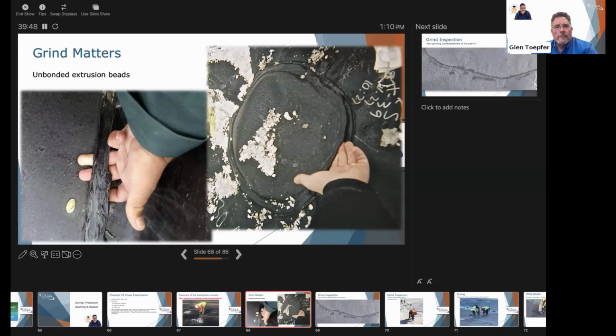And these welds, these extrusion beads, even if you have a pinhole and you're using it to cover a pinhole, which I never recommend. I think pinholes should be patched, but I've seen it personally where they ran an extrusion bead over a pinhole. They dropped an air test needle or something, and I happened to see them do it, and they did that, and they're like, "Oh, it'll be okay, it'll pass," and they vacuum boxed it and they spark tested it, as it was a conductive material. Both passed, but it would fail in the long run, so I made them cut it out and repair it. But these things will lie to you and give you a false sense of security. But again, you're not going to know that it wasn't ground if you weren't there when they put it down, unless the bead's laying there like it was on the project I was on.